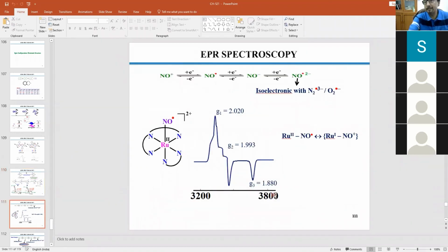Okay. And then another example I have given is a very nice example that NO-like quinone can also exist in different oxidation states. Now, this is one molecule which could be characterized crystallographically absolutely without any doubt. And if you record the EPR, you should expect a one-line EPR for the NO radical like this. But in the experimental EPR, you could see the anisotropy. And that anisotropy could be interpreted similarly to what I talked about in the earlier case, that this is the majority component, and if you allow it to undergo intramolecular electron transfer, then the unpaired electron will move from here to here. As a result, this will be reduced to Ru1 and this will be the NO plus.